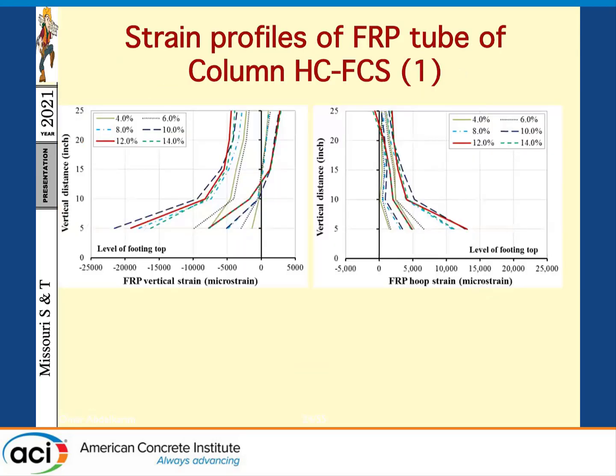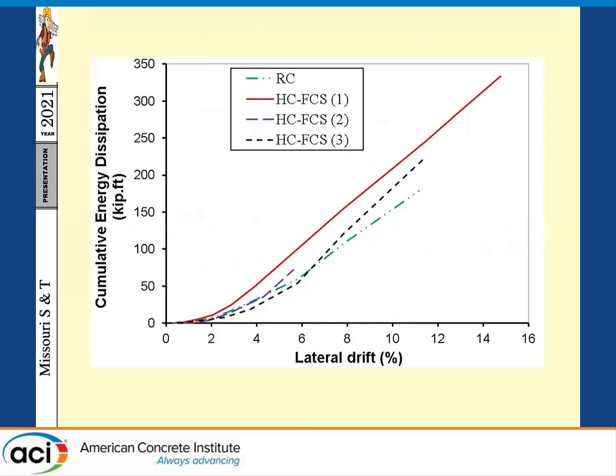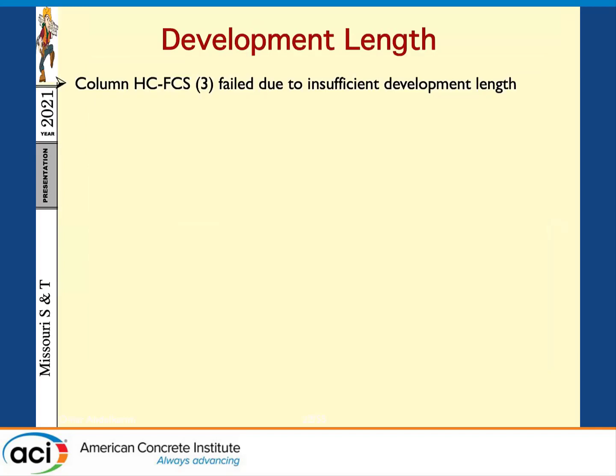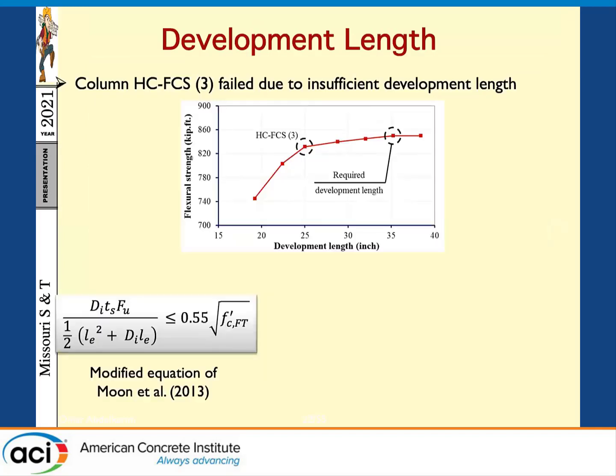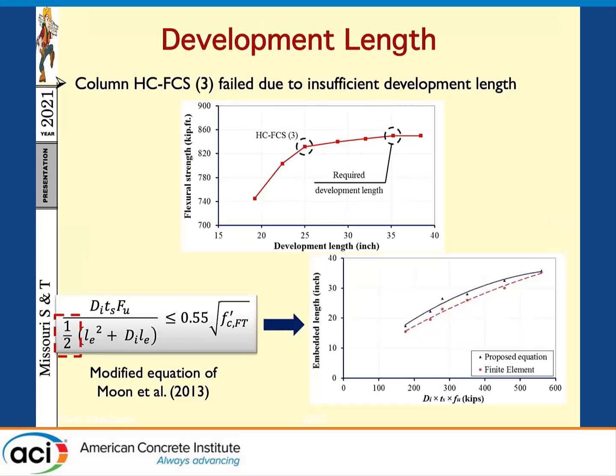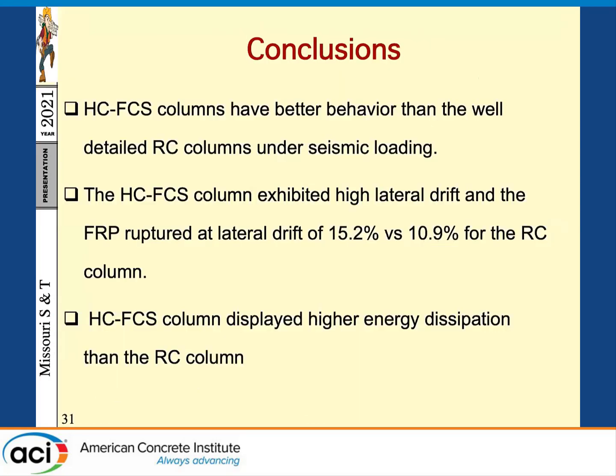And then we also looked at the vertical strain. This is along the height. Those are just the strains. And then we propose an expression for the embedment length. How long you would like to embed the FRP, the steel pipe inside your footing to develop the full capacity of the columns.